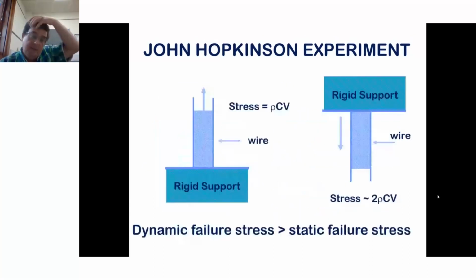So basically, if you've got a weight hitting the bottom of the wire, then it puts the wire into motion. And so the stress you're developing will be density of the wire, the sound speed in the wire, which we know is related to Young's modulus, and the velocity of the particles within the wire. So the stress developed was equal to rho density C V.